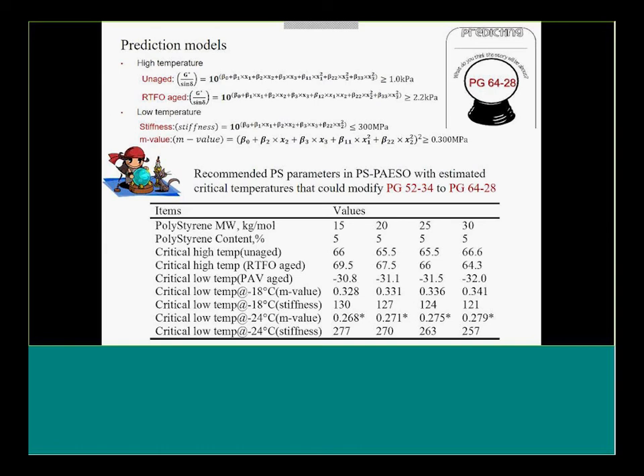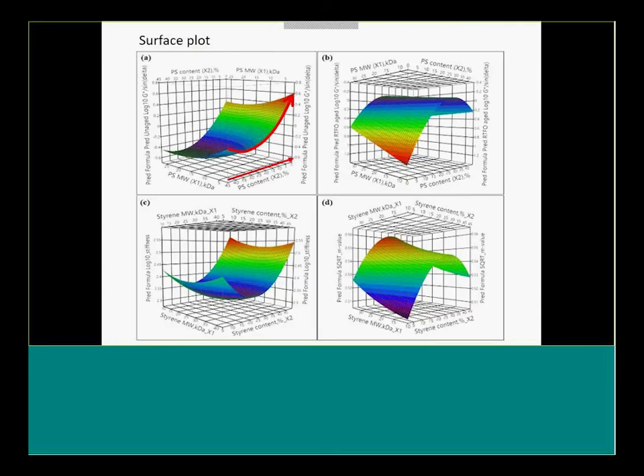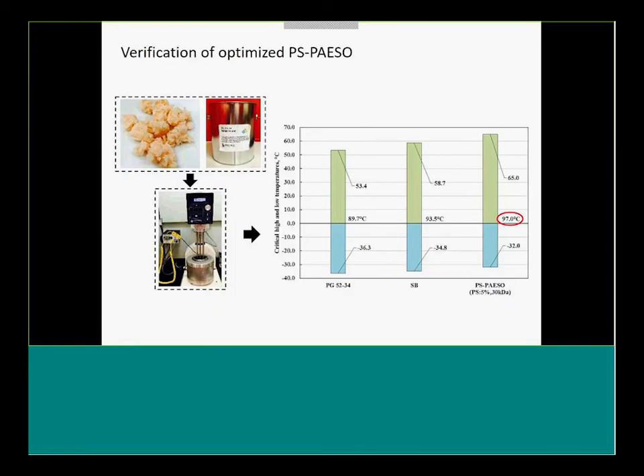And so we come out and we say, well, basically if we want to get there, we want to push that molecular weight up higher to get us to the lower temperature criteria here on the one hand. All right. But the polystyrene content's only at 5%. That's a lot lower than what we're buying in today's block copolymers that are 30 or 35%. Okay? So lo and behold, we can come up with what we call surface plots, and we can come up with what we believe is the optimum formulation. We produce the polymer, and then we blend it in the asphalt, and look, we've done a great job.